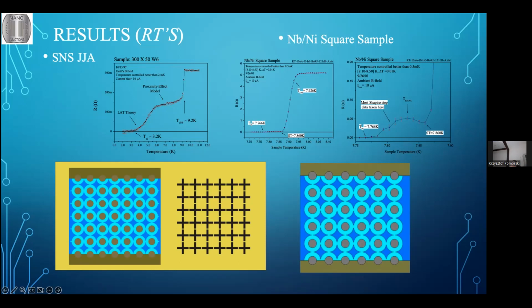So somehow this yellow-blue is simply weakened superconductivity, I presume. Exactly. There's no other way. So definitely the system described by you could be grasped by Ginzburg-Landau formalism and by Bogoliubov-de Gennes formalism. And my understanding is that all these materials are pretty much BCS superconductors. There are no high Tc. No high Tc. So then the level of predictivity and understanding of phenomena is much higher than in the case of high temperature superconductors, which is a good thing.